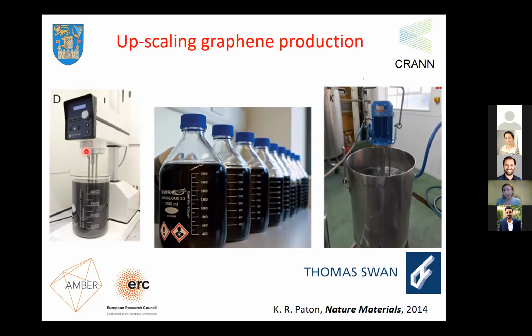This is something that we shouldn't say in public, but the very first test of exfoliation using a shear mixer was with a kitchen blender. So we went to a shop, we bought a standard kitchen blender, and then we used the usual method, solvents, graphite flakes, and we gave a little mix, and indeed we realized that we could exfoliate graphite with that method.